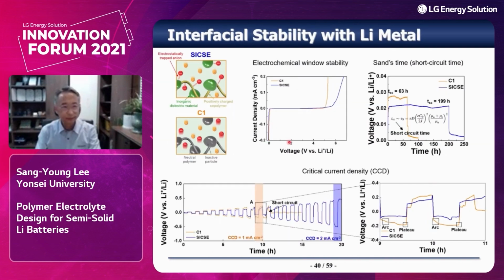Here is the interfacial stability with lithium metal. As you expected, our single ion conductors provide benefits in the electrochemical stability window. We have also measured the Sand's time, and as you can see, a substantial improvement was achieved by incorporating single ion conducting capability. Also, we measured the critical current density, which is 2 times higher than the control sample, and stable plating and stripping behavior was observed with our single ion conductor.